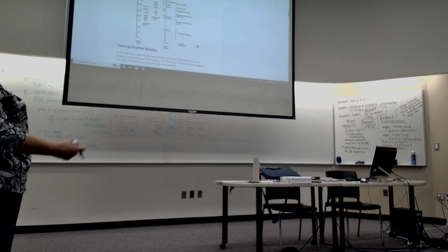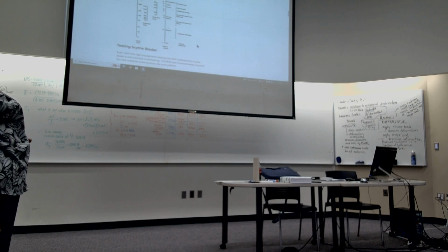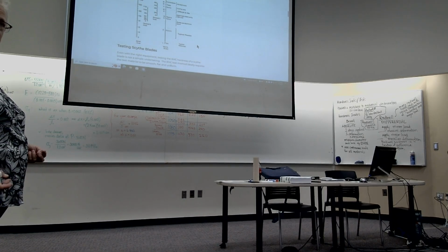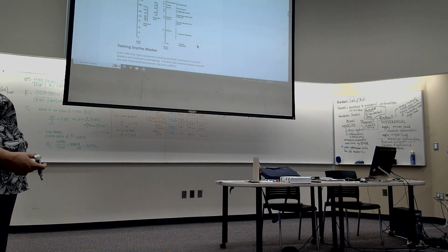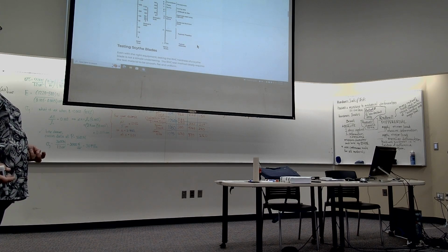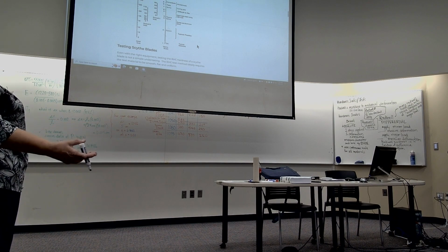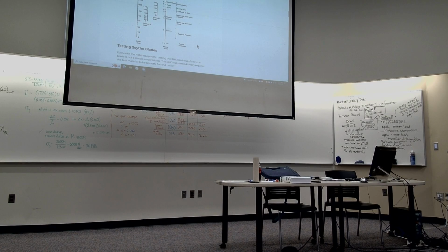High strength plain carbon alloy steels, not tool steels, will have a hardness of sometimes as high as 65 Rockwell C. But those same steels that have been, say, annealed, not heat treated, can have a hardness of Rockwell B 70. And if you want to quantify how much harder you've made the steel, you can't really do it because those two scales don't overlap.